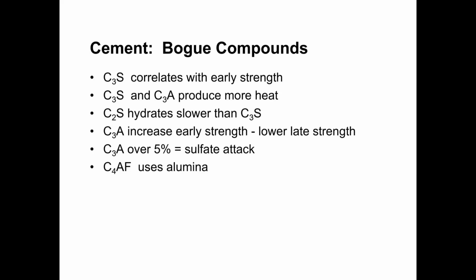C2S adds to the concrete strength as well, but it hydrates more slowly than C3S, so it doesn't contribute as much to the early strength gain as the C3S. C3A increases the early strength of the concrete, as would be expected, since it produces more heat of hydration. However, the C3A can adversely affect the late strength gain. So C3A may contribute to your initial strength, but it may negatively affect your long-term strength. C3A also has the problem that it contributes to sulfate attack. So a C3A content over 5% has an increased potential for sulfate attack within the concrete.